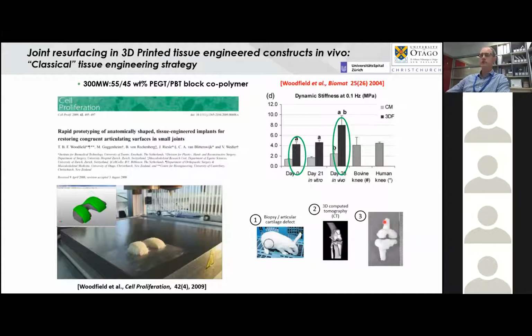So essentially we were trying to look at the macro scale anatomic structure here that was porous with the right mechanical properties to match articular cartilage, and we were then able to take autologous chondrocytes from the rabbit and look at seeding and tissue formation over time. So I think this was again one of the first studies where we were trying to look at articulation between two tissue engineered constructs that have been fabricated using melt extrusion and seeding of autologous chondrocytes, with the idea of looking at regenerating or surface joint resurfacing for cartilage repair.